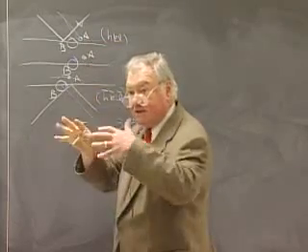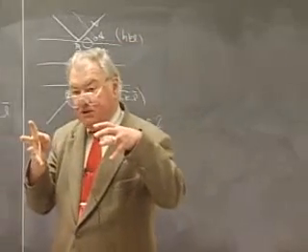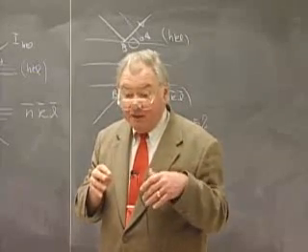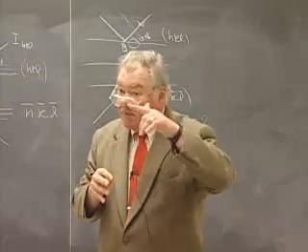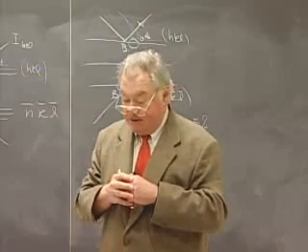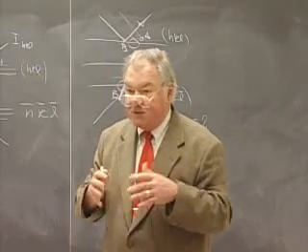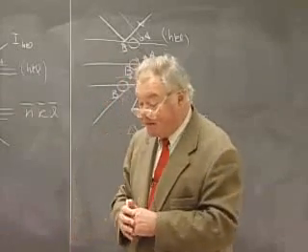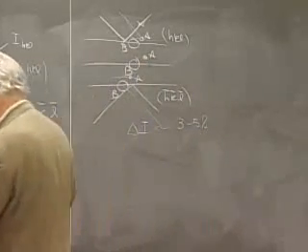And if the crystal has an irregular shape, the absorption, which can easily be factors of 10, 20, or even more, would be different for X-ray beams coming in those two orientations. So in any case, as I say, I won't say anything more about it, but that's the meaning of the Laue groups. These are the point groups that have inversion in them.